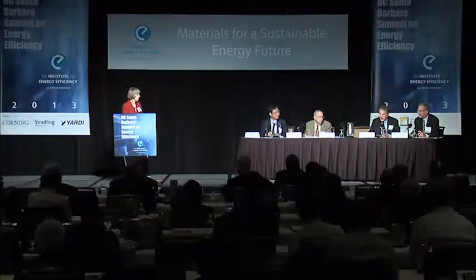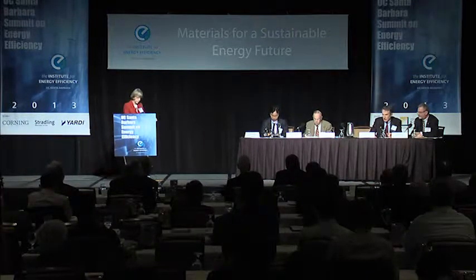Okay. Bob, and then... Well, I wanted to add 2 things. One is that you certainly don't escape the problem of critical materials, because the high efficiency multi-layer photovoltaics that play a role in concentrated solar power involve things like indium phosphide and gallium arsenide and so on, and germanium, all of which are either on or close to criticality lists. And the other, and I think I'm echoing what Sangwon said, is that the manufacturing processes that have evolved over long periods of time favor the materials that we use now. Cadmium telluride is popular because it's a manufacturer's dream, even compared to silicon. And the issues associated with manufacturing these high efficiency multi-layer PV materials are, at the present time, really outstanding research problems.